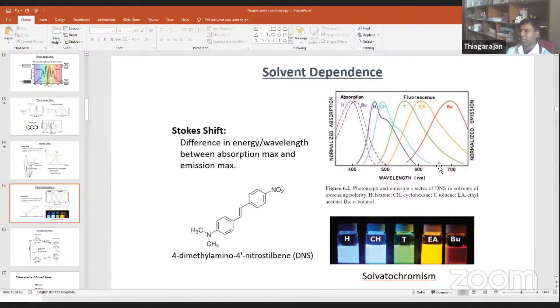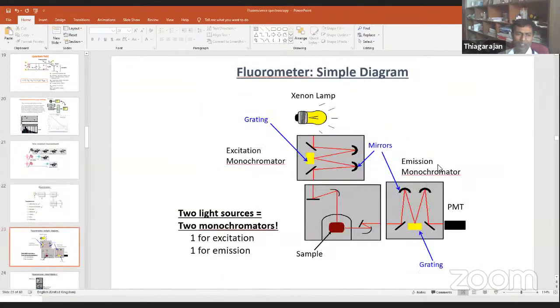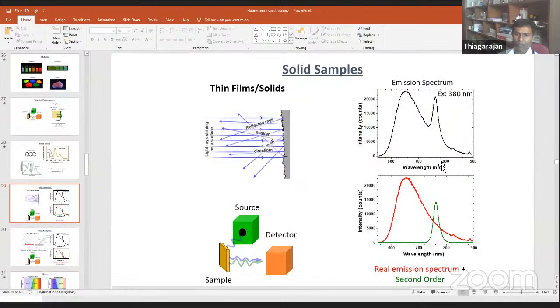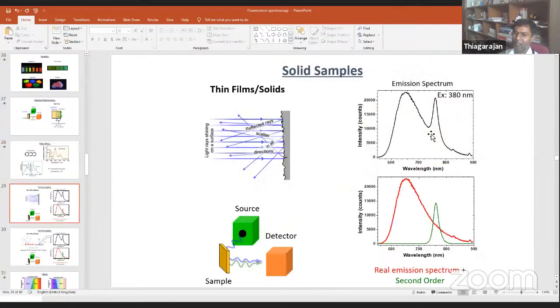Conjugated on a nanoparticle, it's very difficult to say what kind of nanoparticle and the size of the nanoparticle also. Sometimes you can get the scattering also. If the scattering is high, it dominates the fluorescence. So if it's a second harmonic, the scattering will be like this only. If the scattering is very high, you think that this is an emission, but it's not an emission.